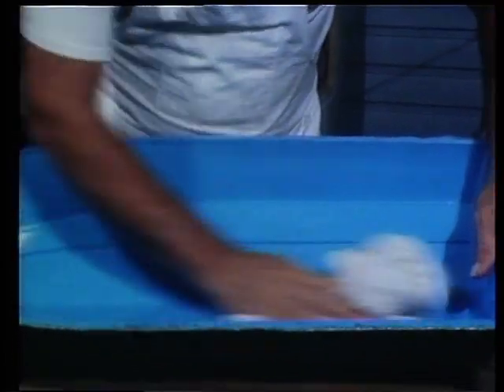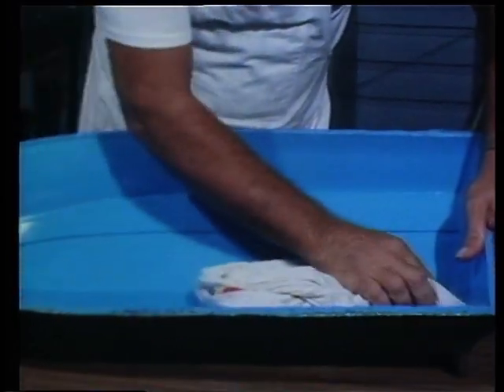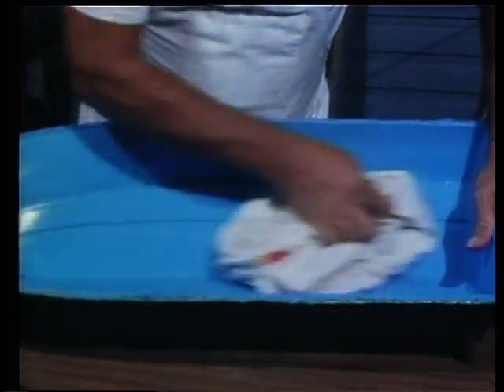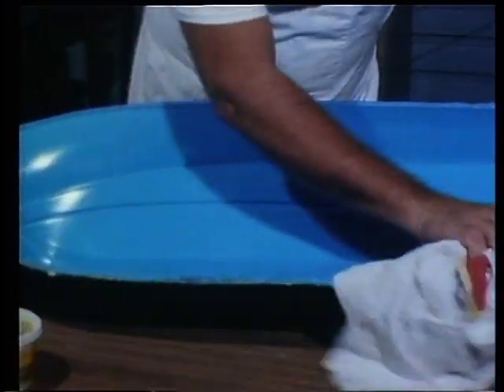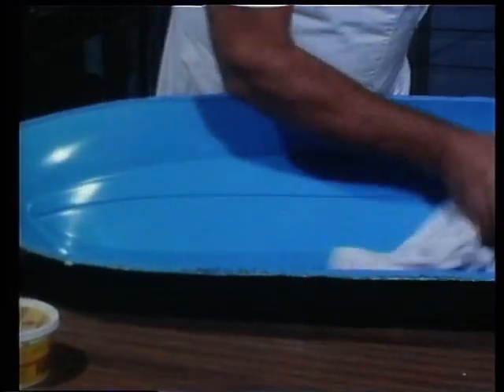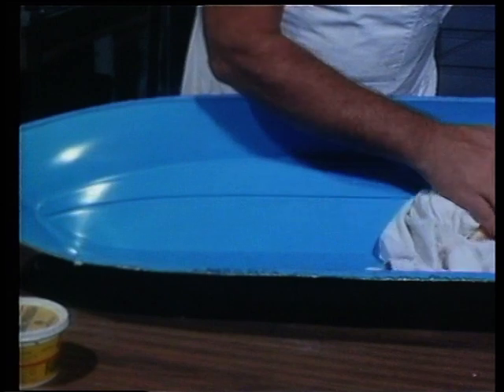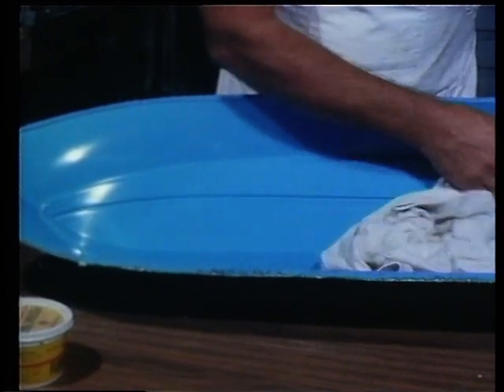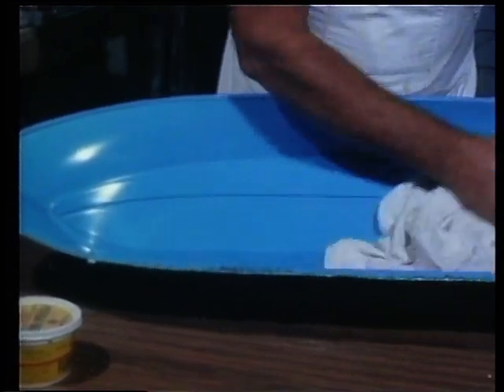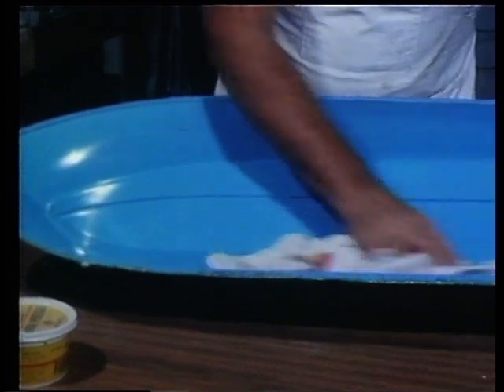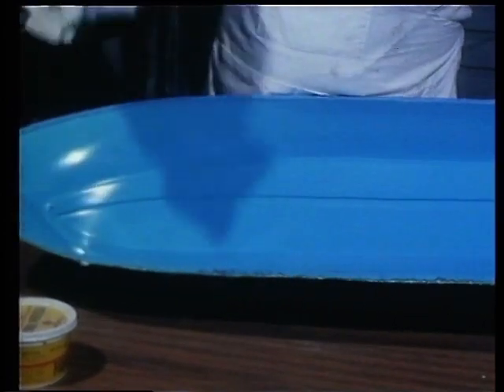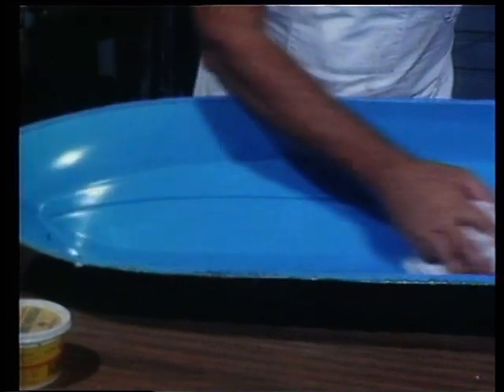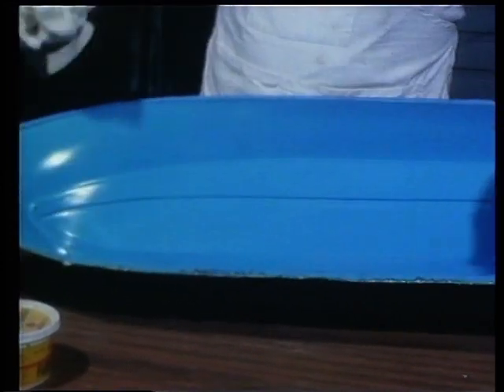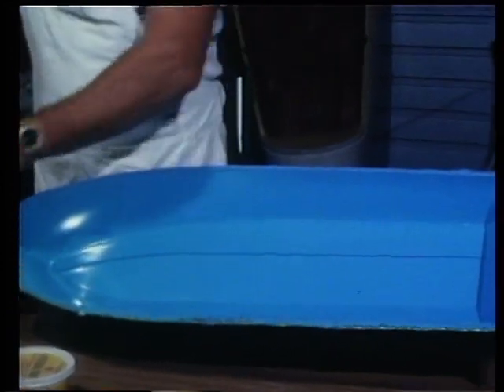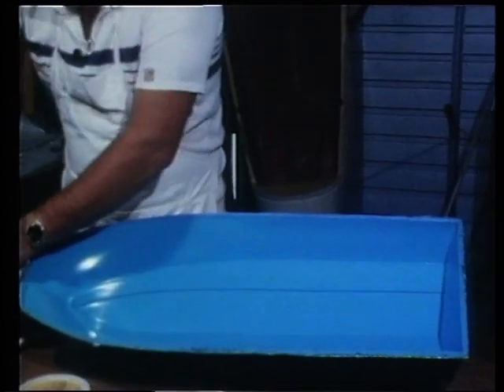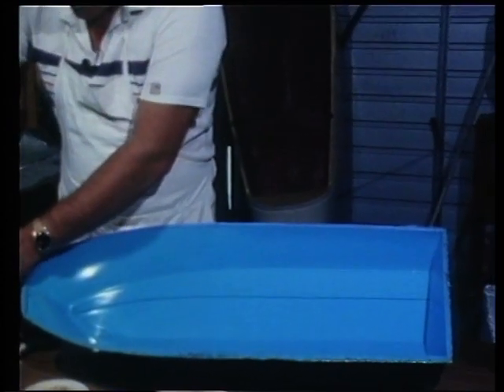Now, as you can see, there's a gloss coming up inside that mould, indicating that I've removed all of the wax that I first applied. Now, normally, if the mould hasn't been used before, you wax it at least twice and preferably 3 times. Again, a belt and braces policy. You make sure that each operation is done properly, in this case by repeating it, but this mould has been used before, so that application of wax will prepare the surface for the liquid release agent.